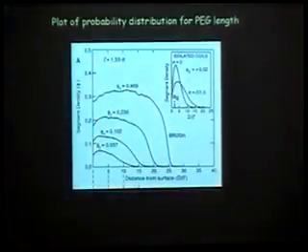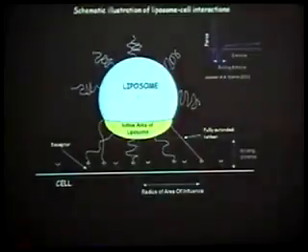So here is a molecular dynamics type calculation from Vladimir Torchilin's group showing the probability of existence at different lengths for polymers. And this is a reduced parameter that is proportional to the molecular weight of the polymer. And the idea being that the larger this parameter gets, the longer the polymer molecular weight, and the larger the fully extended length. Notice that these things have a relatively flat probability of existence until you hit essentially this cutoff dimension and it drops off like a rock. And that's the fully extended length that we consider in the calculations.